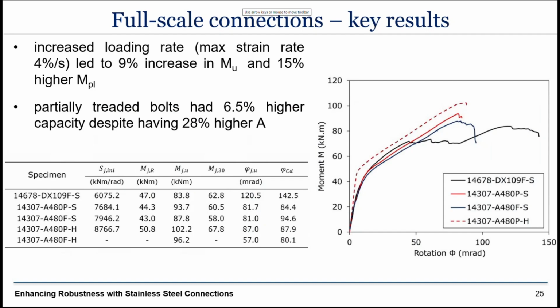So we found that with increased loading rate, the maximum strain rate we recorded using digital image correlation was 4% per second. In reality, it must have been a bit higher than that, because we could only see the side of the plate and we could see the strain through the thickness. That led to an increase in ultimate capacity of 9% and also significantly higher plastic resistance. If you compare the 2 red curves, the dotted one, which is higher than the continuous one, is at high strain rates. Because of that, we have a significant increase in the yield and in the ultimate resistance, about 9% in ultimate resistance, 15% in yield.